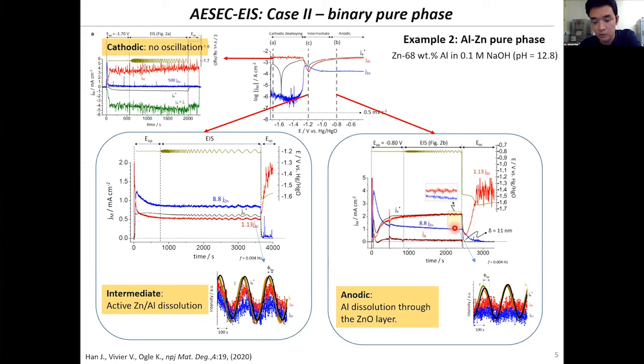Whereas when we increase the potential to minus 0.8, we see this nice increase and decay of the zinc signal as a function of time, which means that a zinc passive film is formed on the surface. There's still some oscillation, but it is really attenuated. We are not really seeing the oscillation of zinc as clearly as before, whereas aluminum still showed this nice oscillation. That means we propose that aluminum dissolution in this case occurred through this zinc oxide passive film formed on the surface.